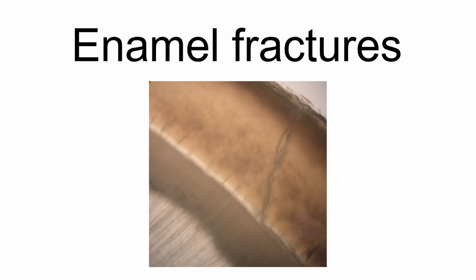The processes involved include them creating stress shielding by increasing the compliance of enamel next to the dentin. Decussation is another factor by which cracks form wavy stepwise extensions that arrest their further development. Enamel tufts also self-heal through a process of being filled with protein-rich fluids. Odontologically, they can be filled by light-cured composite resin when applied in 2 applications.